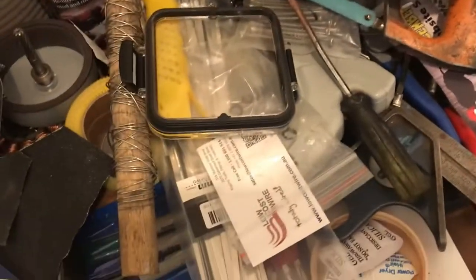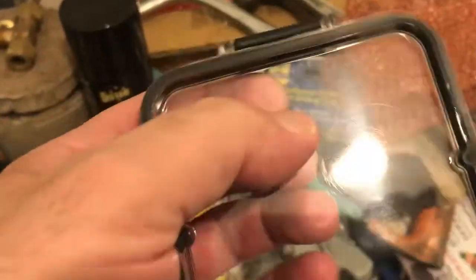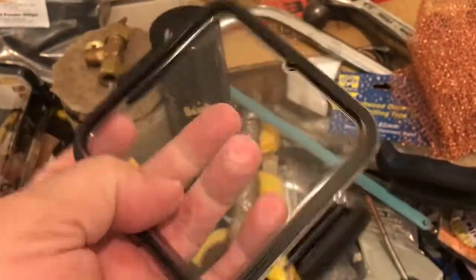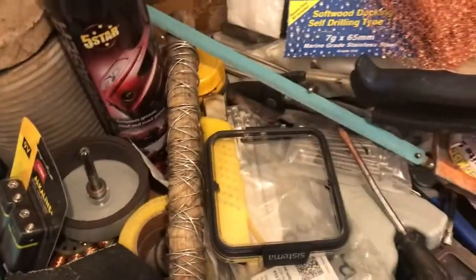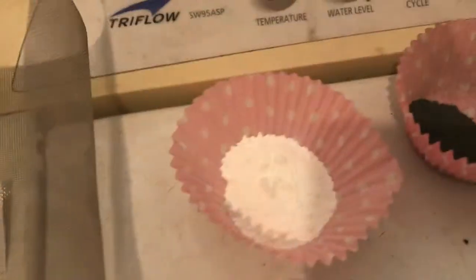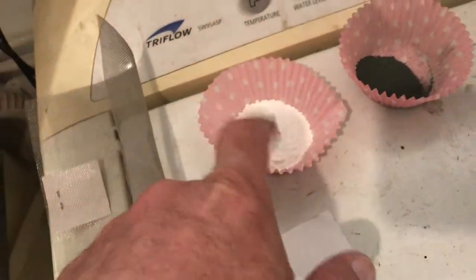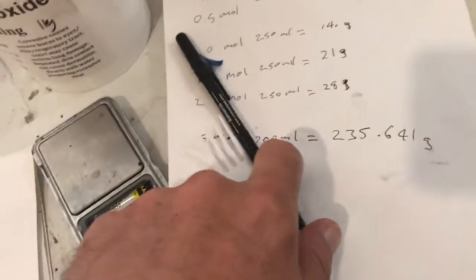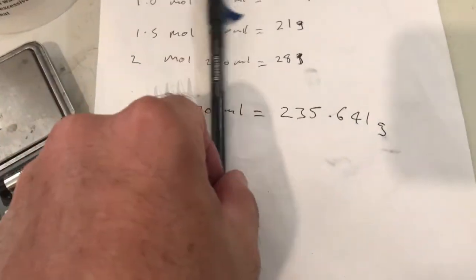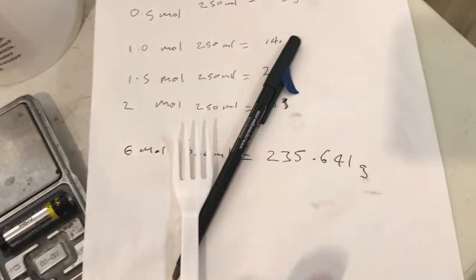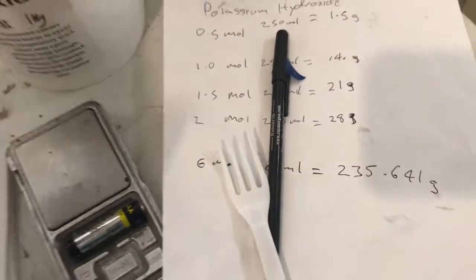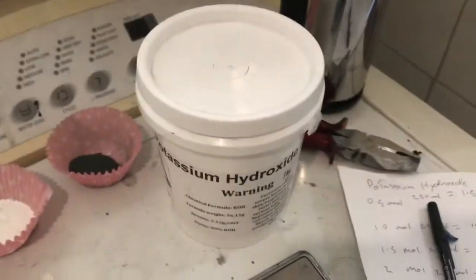I have a good little seal, so the battery actually works. I might melt some holes through here to stick the electrodes and glue them in, but we don't know if it's going to work yet, so I won't wreck my dish. I'm going to try to put 10 grams of zinc sulfate into the potassium hydroxide. It takes 700 mils. At 6 mol is 235 grams I need. And slowly I'm running out of 1 kilo already. Yeah, you use that stuff pretty quickly.